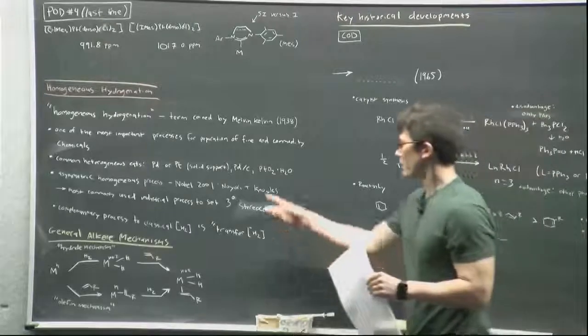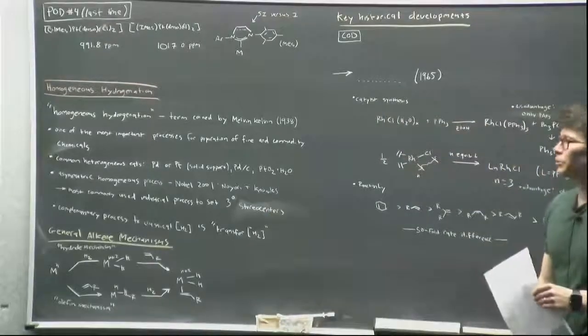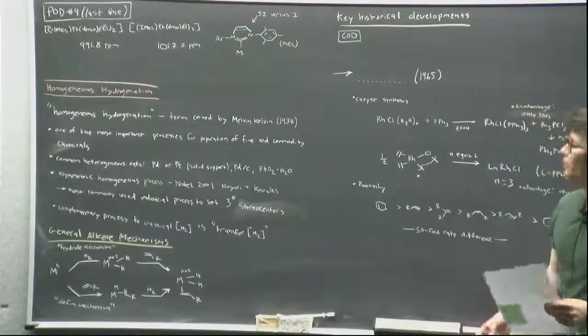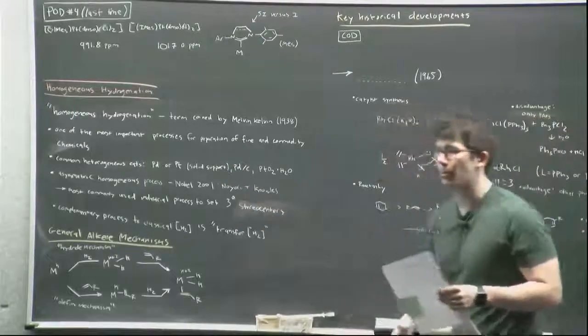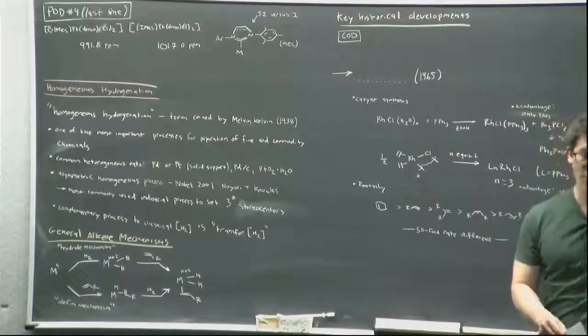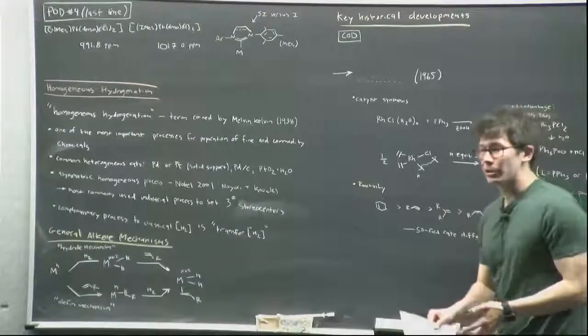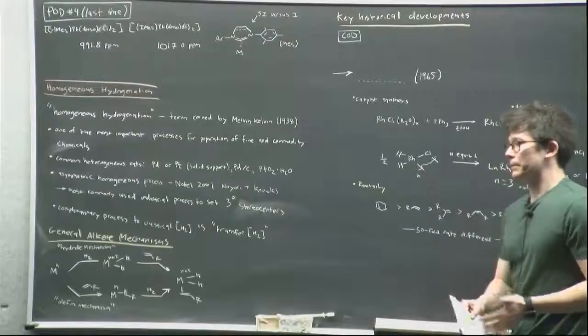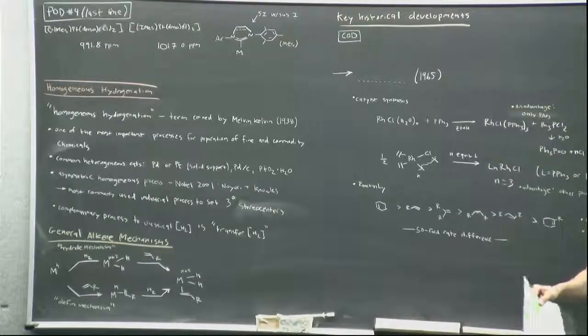And one point I'll make here, and if you've ever gone to a lecture by someone from Johnson Matthey, for example, that specialized in making palladium on carbon, the reactivity can actually vary quite a bit depending on the nature of the carbon support. And so if you have a tough hydrogenation in your total synthesis and you try your single batch of palladium on carbon from Strem, well, first make sure that it's fresh. But even after finding out it's fresh, that might not be the right, say, mesoporous carbon support to enable reactivity with your complex substrate.